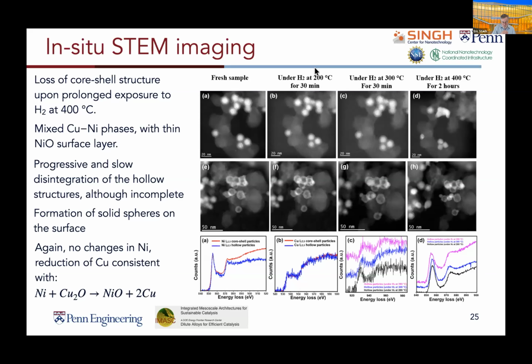That's kind of a standard mode for electron microscopy: if you do look at one region during a reaction, it's always wise to cool the sample down and take a look later in a different region, to make sure that the morphology is consistent in a region where the electron beam has not been. And we did not see any electron beam effects in this case.